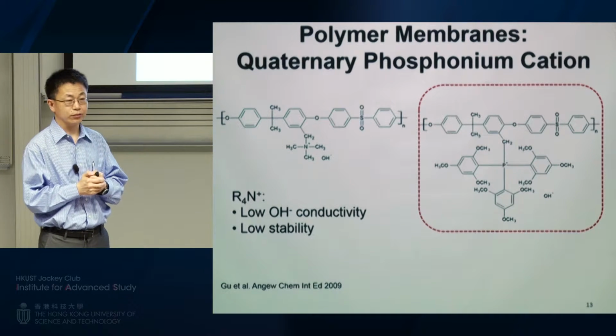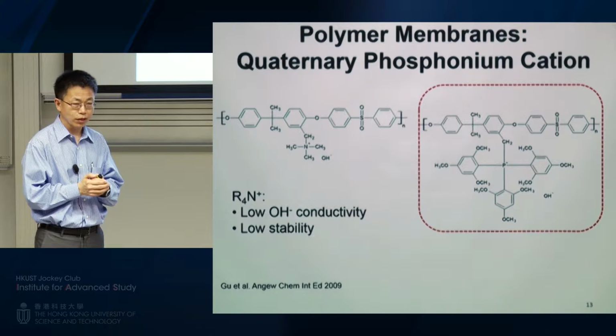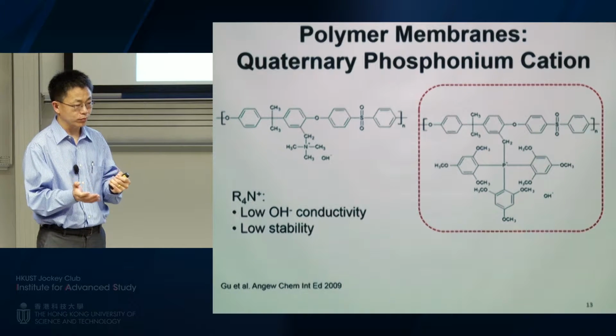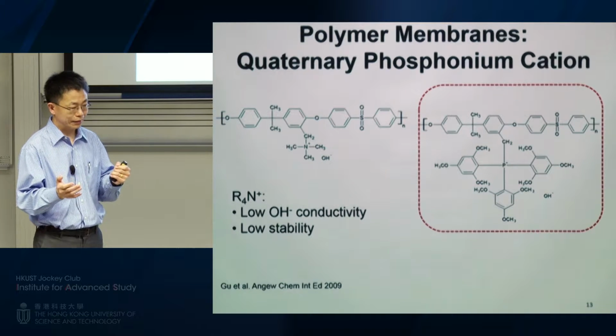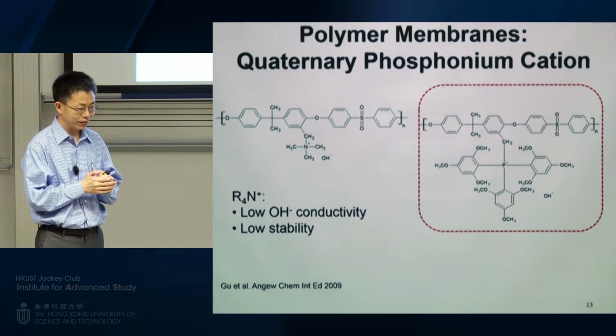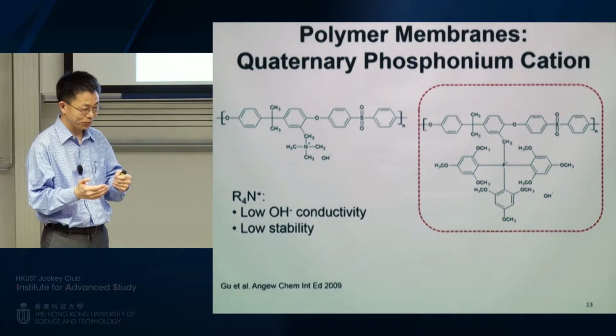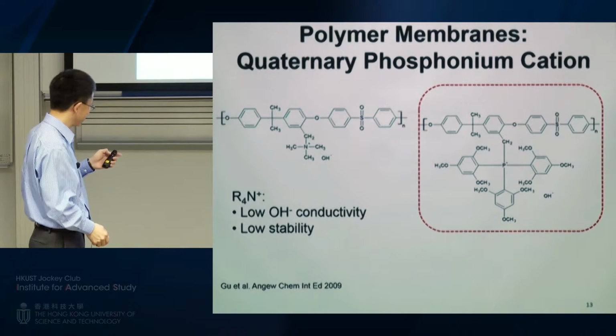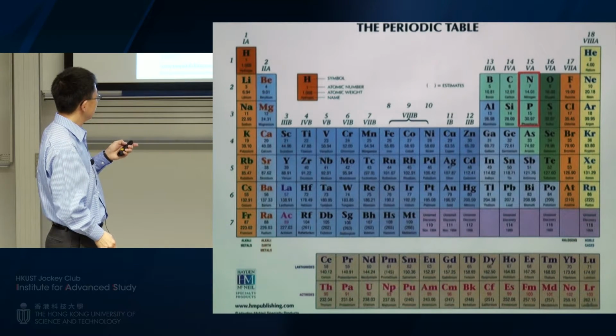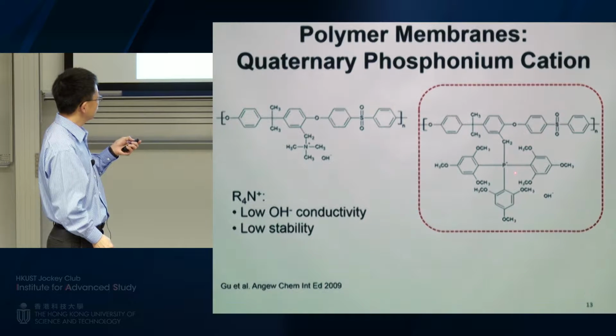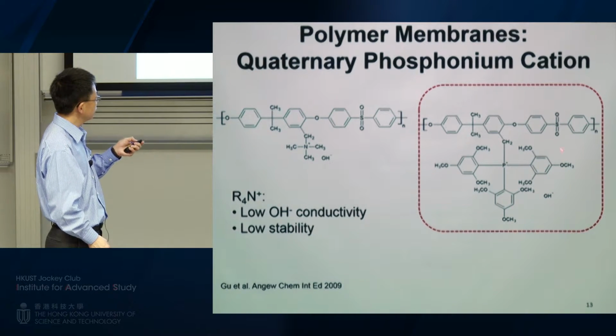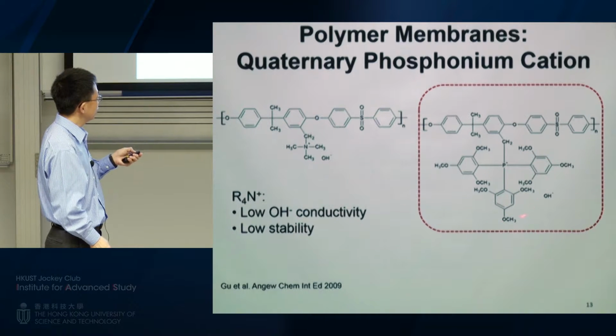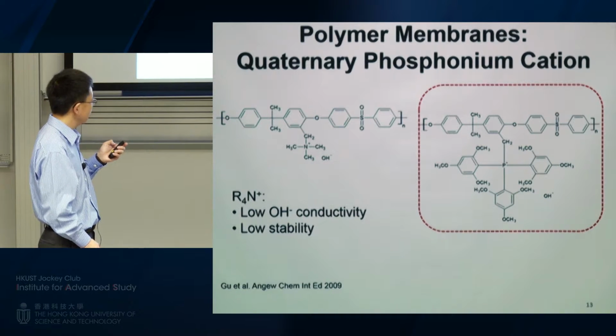What is interesting is, as a PhD student, I used to do a lot of zeolite synthesis. I actually used quaternary ammonium as the template to make zeolite in base environment. And I knew it's just not very stable. So life has a very interesting circle. So what we came up with is this quaternary phosphonium with some very specially designed side groups. So this is not nitrogen anymore, it's phosphorus. And we have these very big side groups. It turned out to be very, very important to have these side groups with this organic cation.